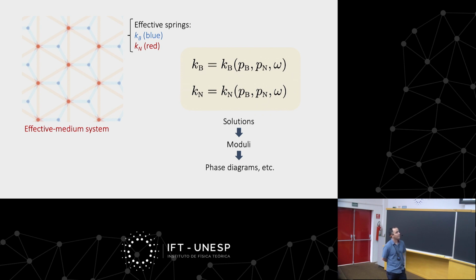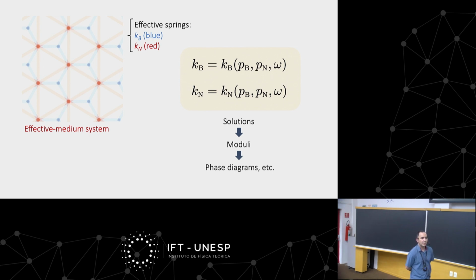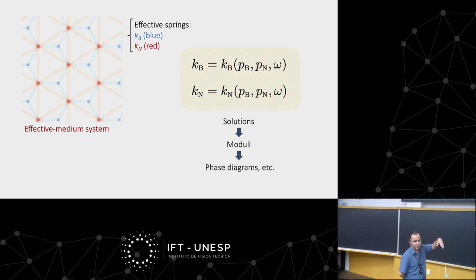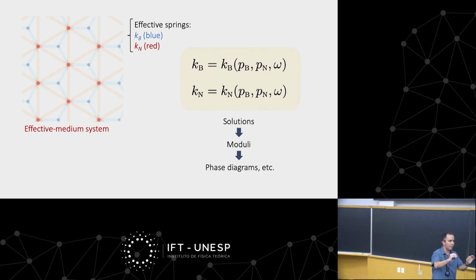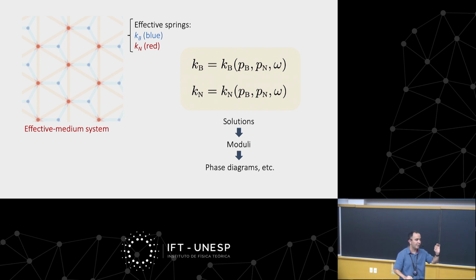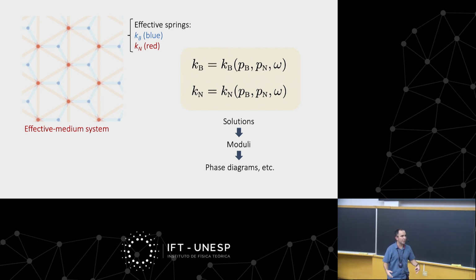Yes? So are you assuming a 2-dimensional model everywhere, or this is just a graph, but you are applying it for any dimensionality? So I can calculate this for this particular model in 2 dimensions. I can also calculate it for a model in 3 dimensions. I have the analogs of this kind of model for 2 dimensions in 3 dimensions. We will use, for instance, the diamond lattice and a combination of a diamond and an FCC lattice. I could give you more details if you want, but anyway. There are generalizations for higher dimension, and also for when you start with a disordered structure from the beginning. The results are essentially the same. The universal scaling is going to be the same.